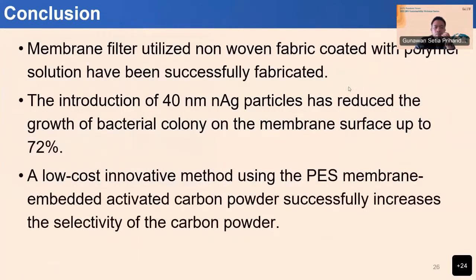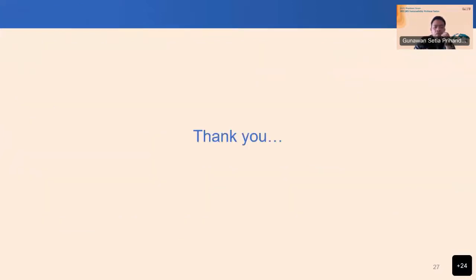Okay, so we can conclude from this work that we have successfully applied the membrane filter for medical masks using the commercial non-woven fabrics. And then also we have 40 nano silver particles that can be used to reduce the bacterial growth on the membrane surface by up to 72%. And also we successfully fabricated the activated carbon disc by using a simple method without high and expensive equipment. It can be applicable for developing countries and also small labs or maybe home industry. Okay, that will be all my presentation.